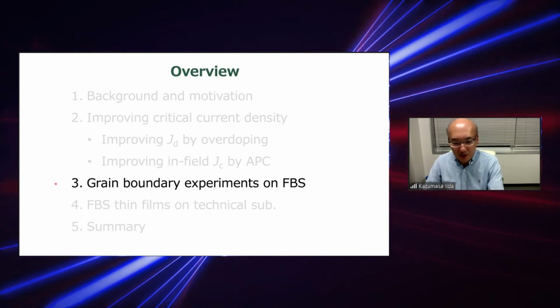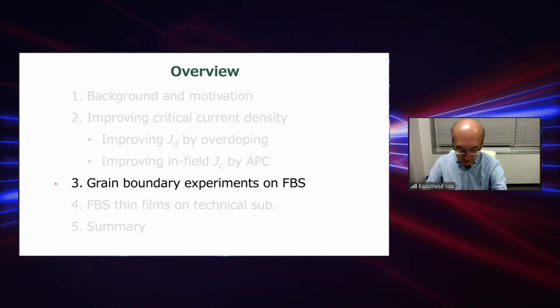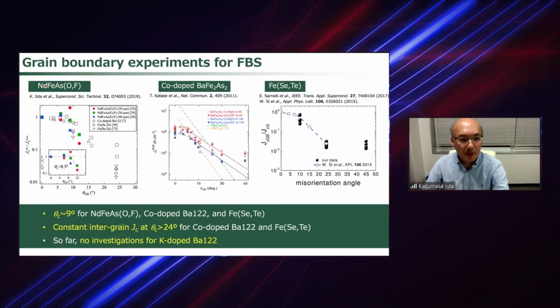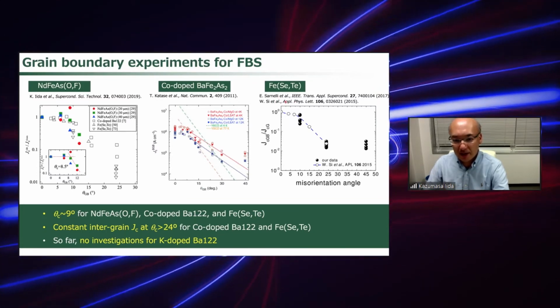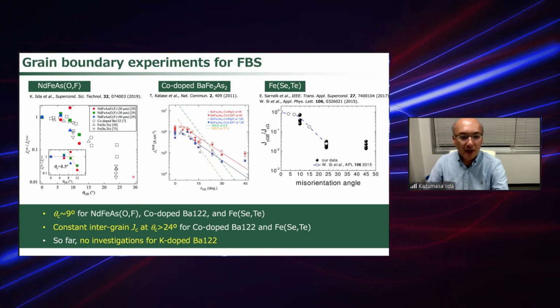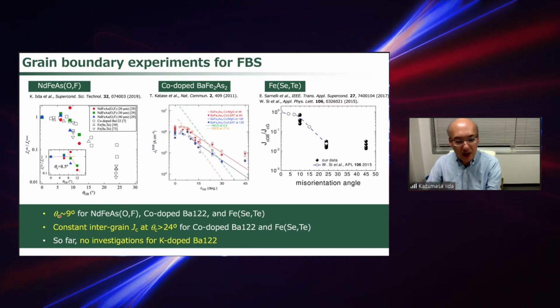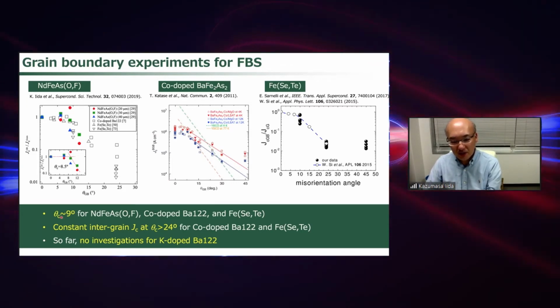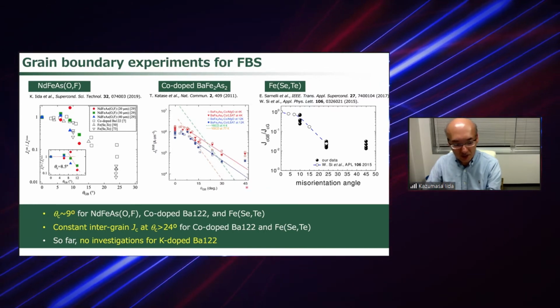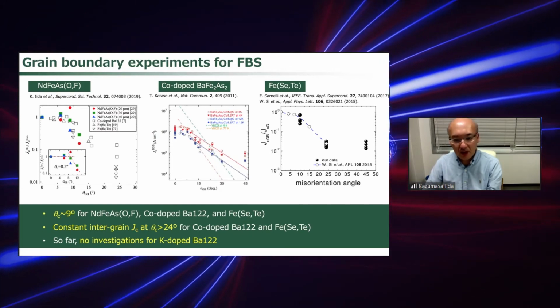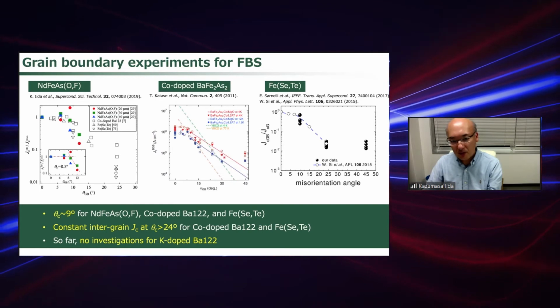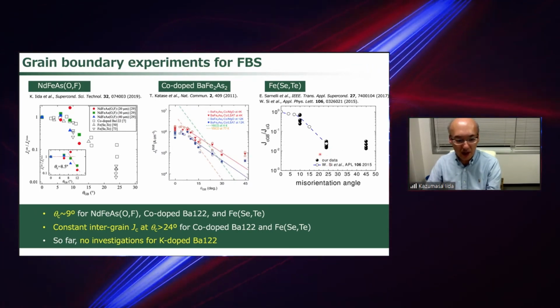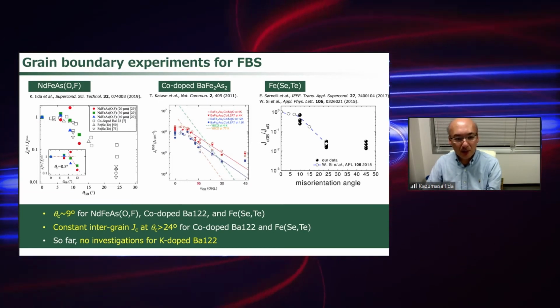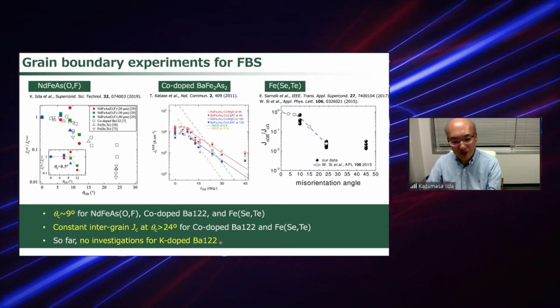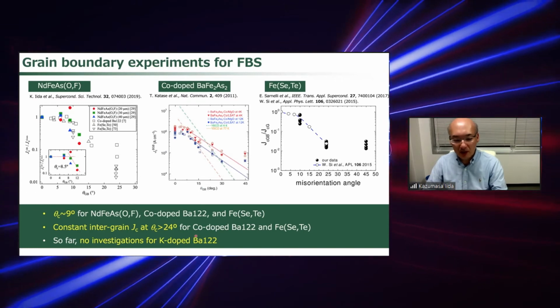So now I will talk about grain boundary experiments on the iron superconductors. So far, grain boundary experiments have been conducted on 1111, 122, and iron selenium telluride. The common feature of the results is that the critical angle beyond which the intergrain Jc decreases exponentially is around 9 degrees for all systems. Also, a constant intergrain Jc beyond 24 degrees was observed for cobalt-doped 122 and iron selenium telluride. But so far, there are no investigations of potassium-doped 122. Again, I mentioned that this is the most important material among the iron-based superconductors in terms of applications.